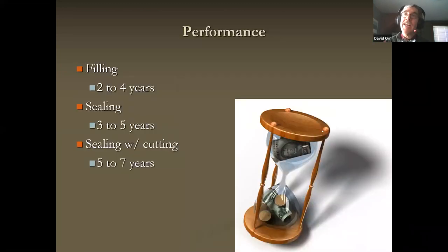Well, filling adds about 2 to 4 years to the life. Sealing, another year, you get 3 to 5. And if you actually do a good job with the cutting, either routing or sawing, you can actually get 5 to 7 years extended life above what you would expect otherwise. Of course, assuming you don't have drainage problems.